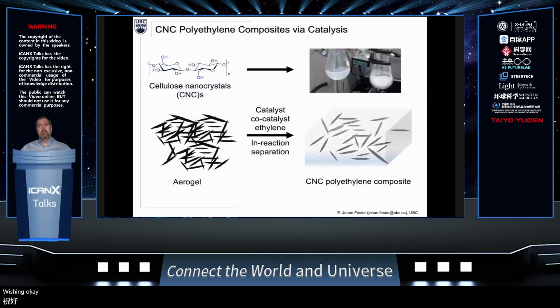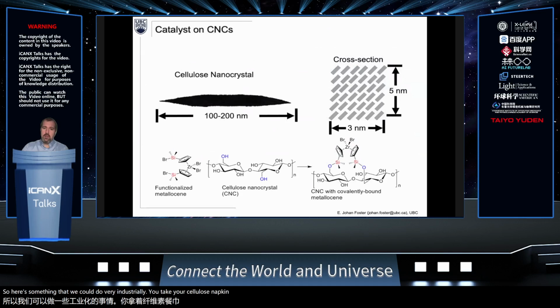Okay, but we wanted to do it better. So we took our cellulose nanocrystals and put a catalyst and a co-catalyst on the surface, and then just pumped ethylene into the solution to make a CNC polyethylene composite. So here's something that we could do very industrially. You take your cellulose nanocrystals and functionalize them with a catalyst for a polymer that's already used industrially. Now, granted, this metallocene is not generally used at scale, but this was what we could do kind of easily in the lab. We functionalize the surface of the cellulose nanocrystal with our metallocene. We make sure it's covalently bound, so we wash away any other solvent.